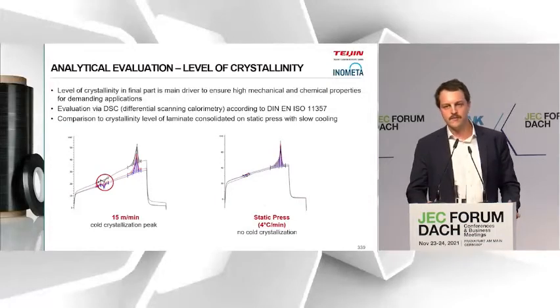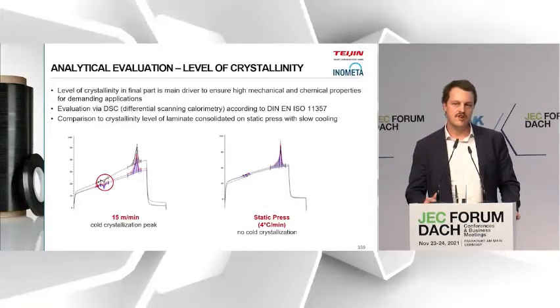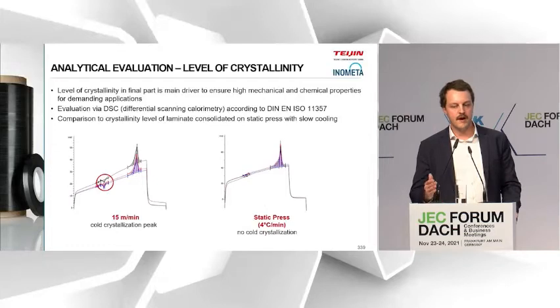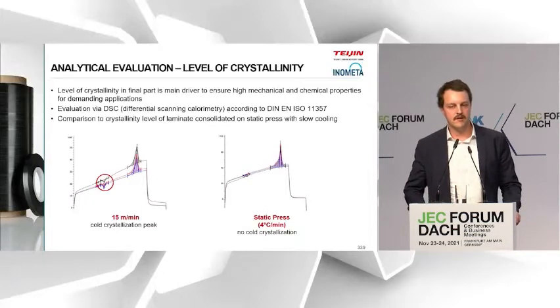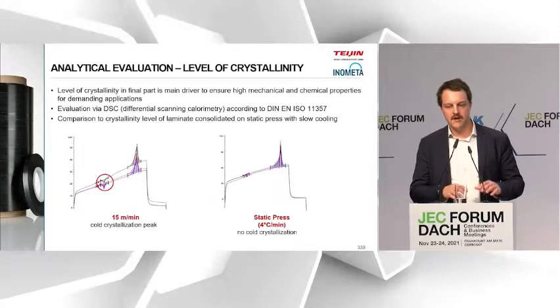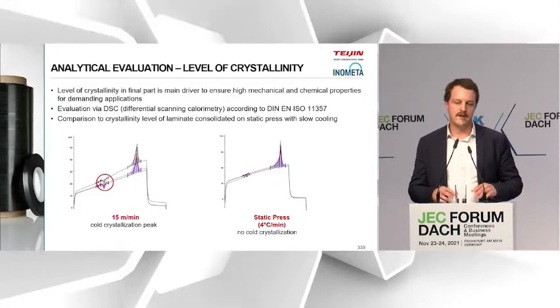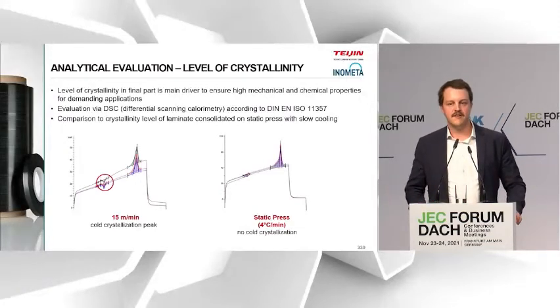That means on the wound samples we produced, we did not achieve the same high crystallinity level when compared to what we have on the right side, the curve from a static press panel. So we compared it to all the background we have with qualification work based on flat panels and coupon testing. And there we do not have such a cold crystallization peak. The issue with the cold crystallization is that you already have a certain level of crystallinity structure, and then if the material sees another heating phase, even below melting, during the application, new crystalline structures will develop, which are not aligned the same as the original crystallization, the crystallites where the spherulites started to grow.